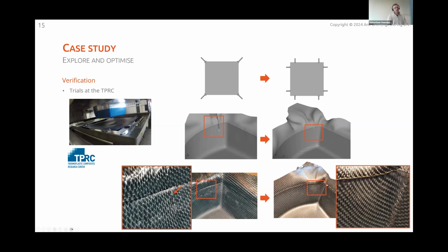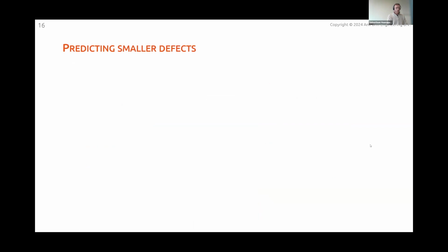And similarly, we tested this configuration, and you see not the presence of such a wrinkle, and you see nicely, yeah, nice uniform shearing of the material in that corner. Yeah, that's all nice. But what about predicting the smaller defects, smaller wrinkles? For that, I would like to talk about this example where we form an aerospace rib.